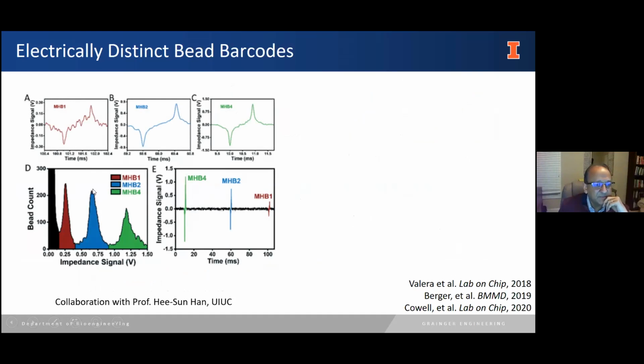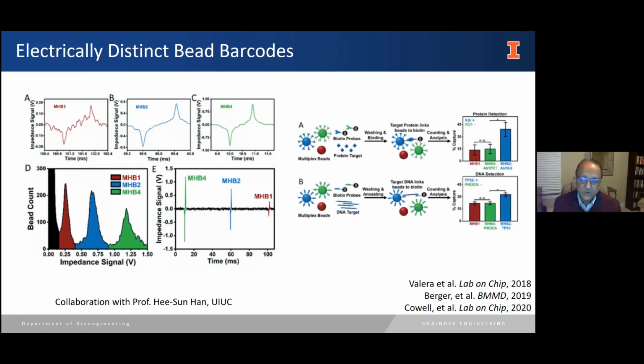So very different pulse height in this case. The electrical signal is very different. So now you can measure 3 different proteins this way, essentially, from the same sample. That's what we are now working on improving. But our paper from last year showed that we can indeed distinguish between IL-6 and PCT, for example, shown here. So this basically shows that using that same platform, we can also now measure proteins.